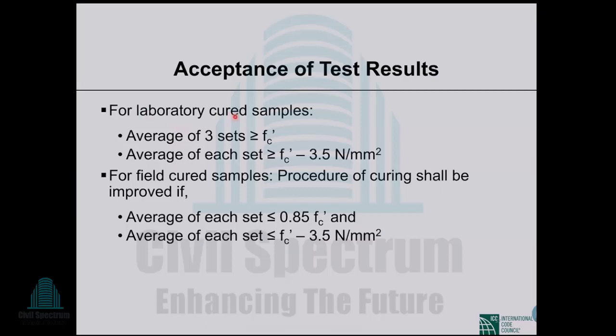So if they are cured under laboratory conditions, then the average of 3 sets must be greater than fc prime. A single set may have an average value which is less than fc prime, but the average of 3 sets must be more than fc prime. The average of a single set may be less than fc prime, but not less than fc prime minus 3.5 megapascal, that is, fc prime minus 500 psi.